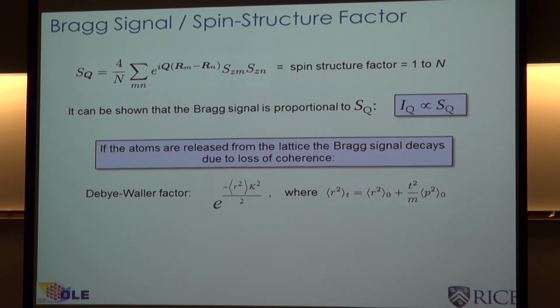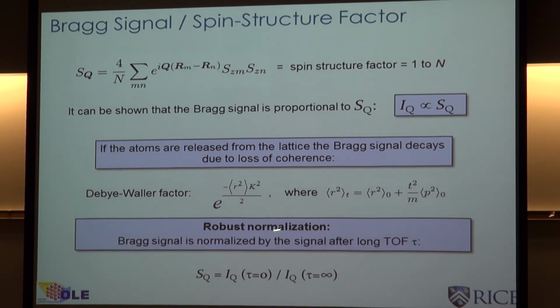So the point is that if we release the atoms from the lattice and then we probe them, they'll lose that ordering. They'll lose that magnetic order very quickly. And the time it takes for an atom to move from one site to another, they'll move to some random place, and we'll no longer see that coherent Bragg signal. And so this provides us a robust way of normalizing the signal after a long time of flight. So we can normalize the intensity of the Bragg signal at zero time of flight to a long time of flight. This long time of flight is only sensitive to the diffuse scattering, to the spontaneous emission. And that ratio then, to the extent it's greater than 1, indicates the presence of magnetic order.